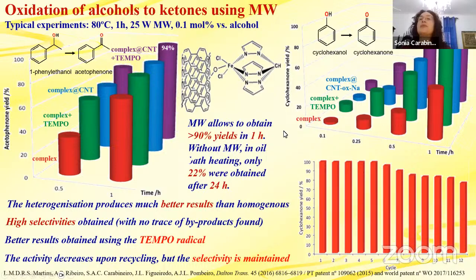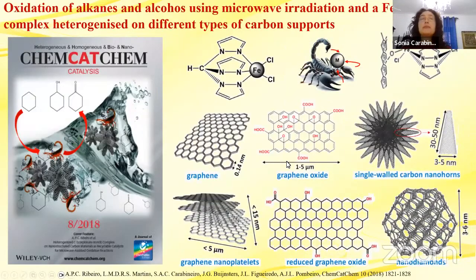And the use of microwave allows to obtain these very high yields in 1 hour, because without microwave, only in an oil bath heating, only 22% were obtained after 24 hours. So you see here, in 1 hour, we obtain above 90% yield using microwave. So that is the advantage.